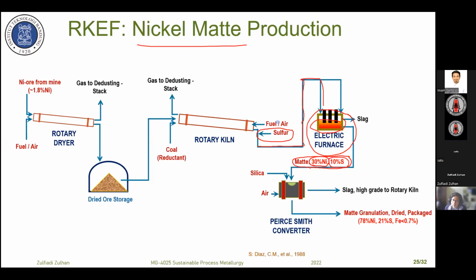And then this semi-product is converted into the final product with a nickel content around 78% and sulfur around 21% by using a Peirce-Smith converter. And silica is added, similar to copper making. Why do they add silica? In order to adjust the slag, fayalite slag, SiO2, FeO slag. This is the reason, similar to copper refining.